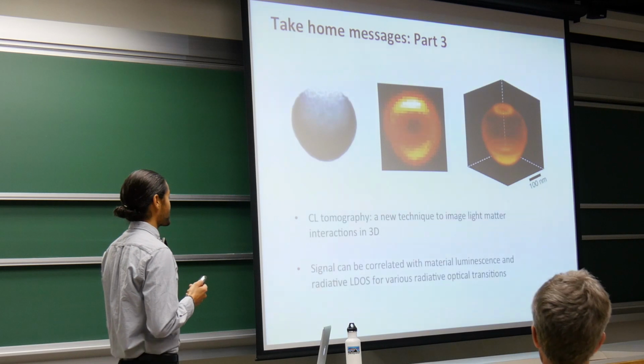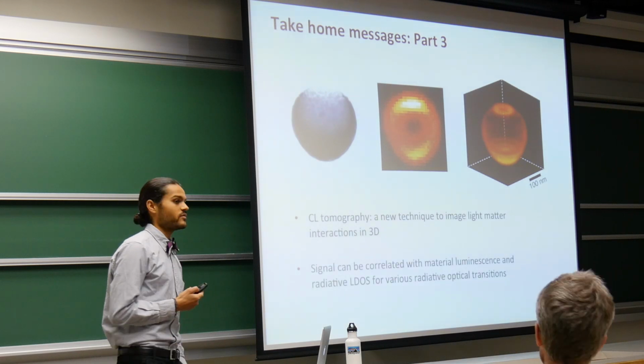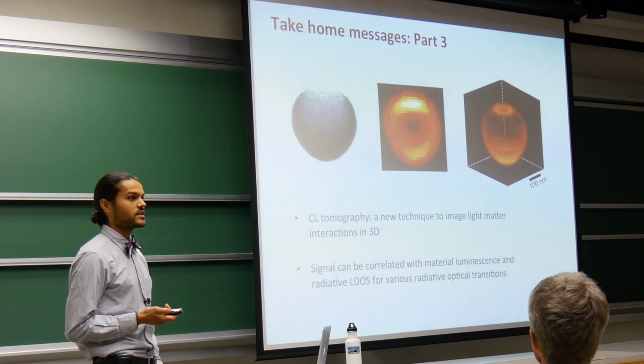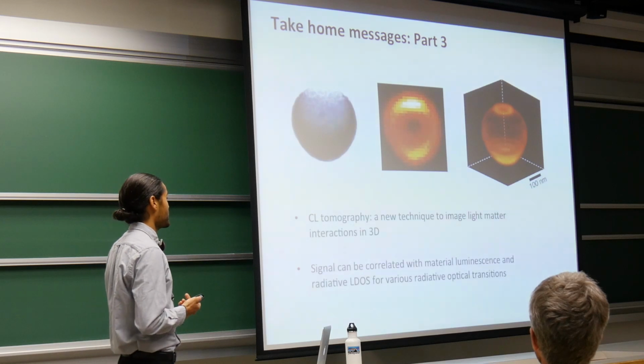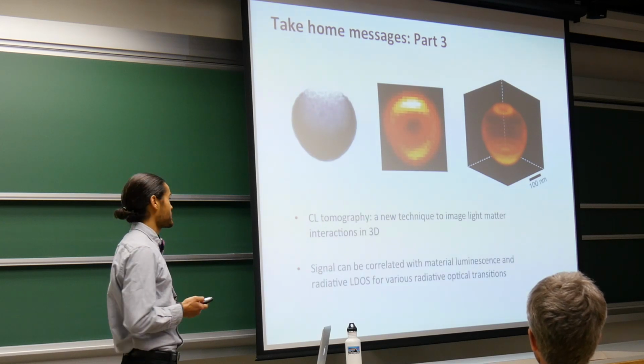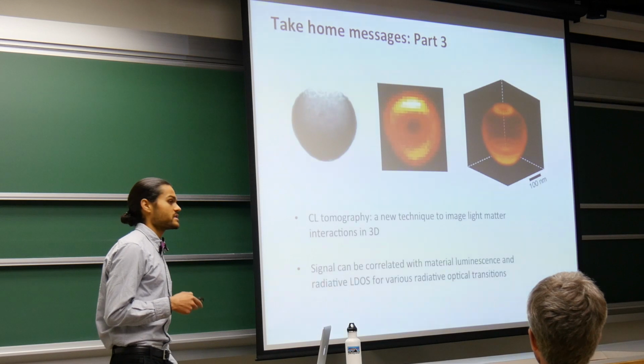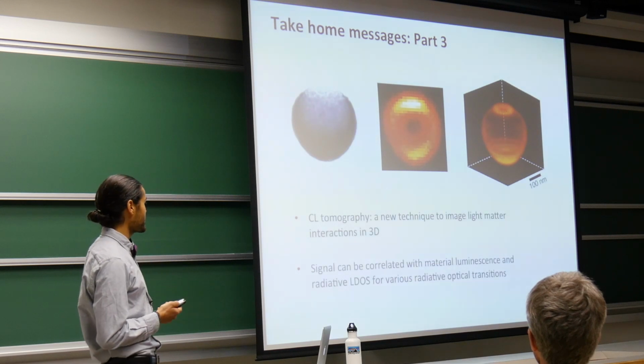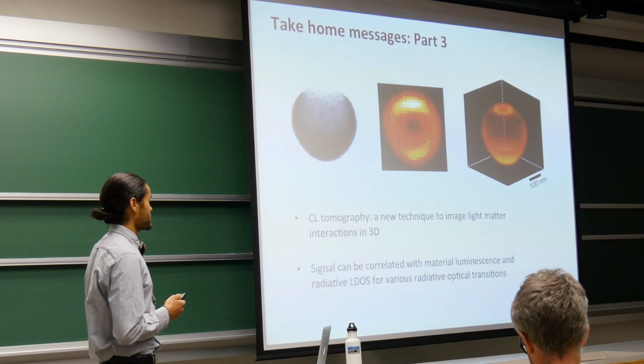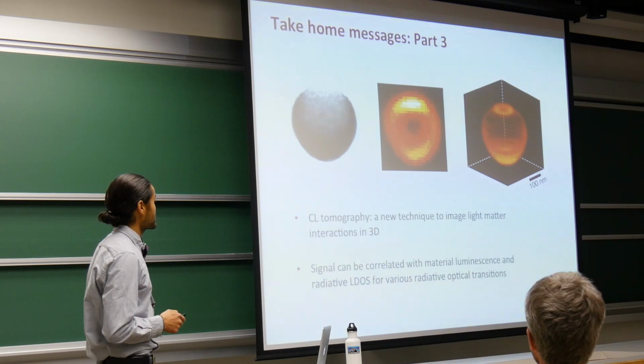So to wrap up this third and final section, I've introduced you to a new technique called cathodoluminescence tomography that can be used to image light-matter interactions in 3 dimensions. And I've showed you that the signal can actually be correlated with material luminescence and the radiative local density of states for these various transitions.